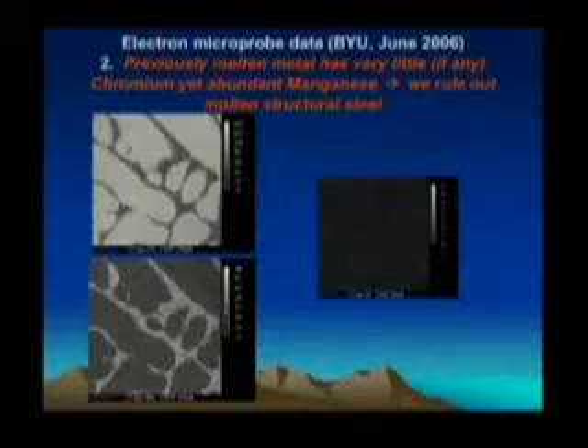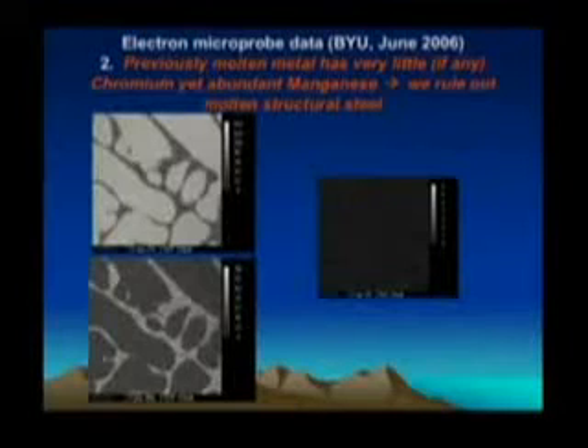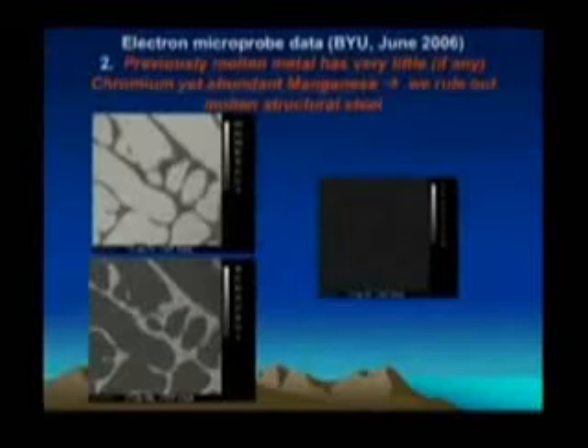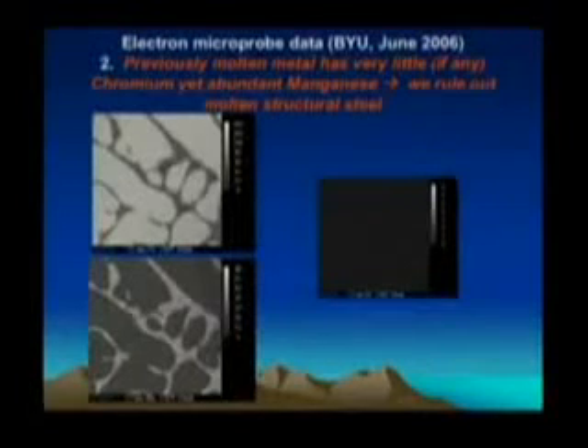It's a big chunk, remember, from the South Tower. Secondly, we see iron again, upper left. On the right is chromium. And what that is, is just noise. There's no pattern. This is just background noise. In other words, there's very little chromium. Now, steel has a fair amount of chromium in it. We're confident that we can rule out molten structural steel, but we don't make that statement conclusively yet until we do some more checking. On the other hand, there's a great deal of manganese, but notice it anti-correlates.